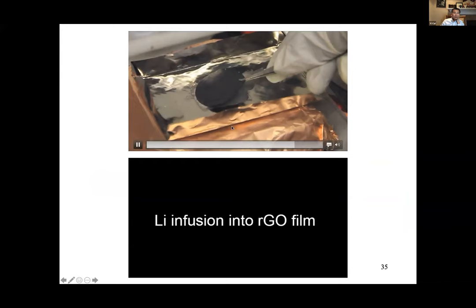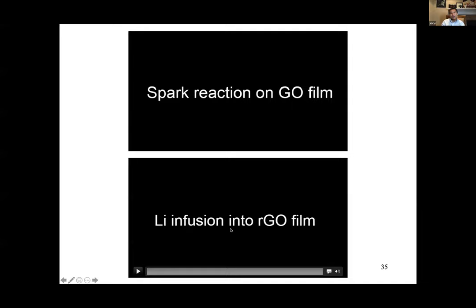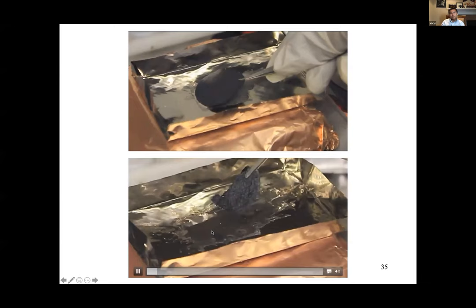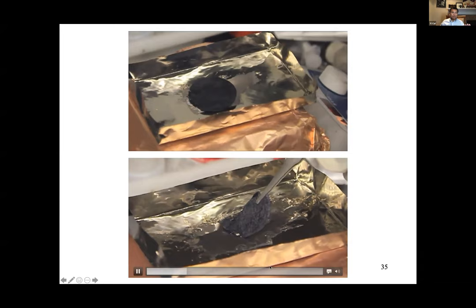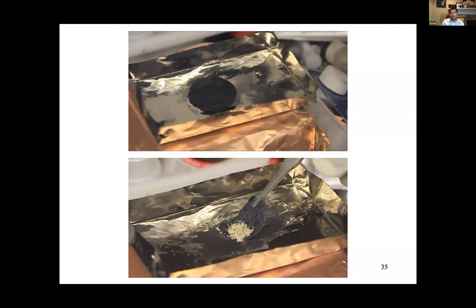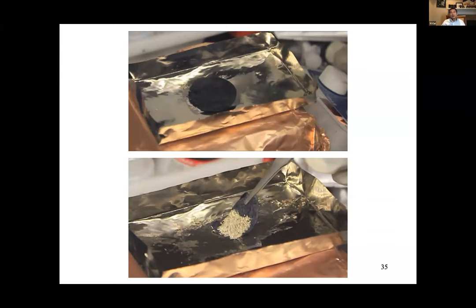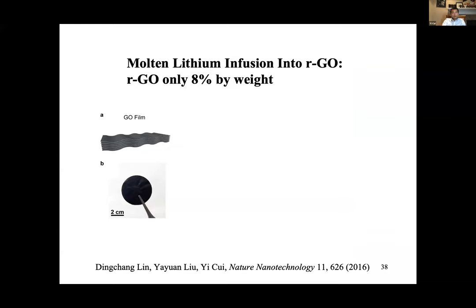This is a phenomenon similar to hydrophobic and hydrophilic for water — we coined the new terms lithiophilic for wetting of lithium and lithiophobic for non-wetting of molten lithium. The graphene oxide has a lot of oxygen functional groups. When you place the graphene oxide stack in contact with molten lithium, there is a spark reaction that creates gas species, opening a gap of nanometers to 100 nanometers between graphene oxide sheets. Then the molten lithium wets through capillary force, going into the graphene oxide quickly, forming a golden color of lithium metal sandwiched between graphene oxide.